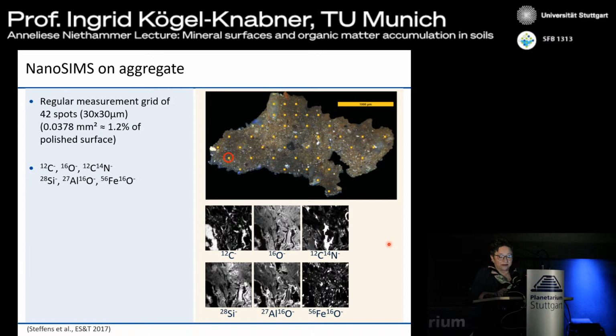And to be honest, we had real problems publishing that because the reviewers said, you talk about one aggregate, and we didn't do 20 aggregates. But we have a very nice coverage of the distribution of these elements in this one aggregate, and a much better coverage than what we get if we work on the plot scale in the field and sample one soil with 3 replicates. So it's really a very detailed study, but it was difficult to convince other soil scientists, but finally it worked out. And with all these data, we had 11 million something points measured.